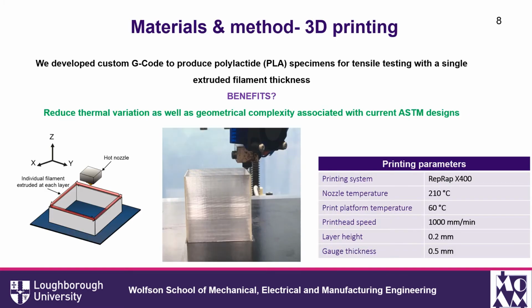To do so, we decided to print our own tensile testing specimen using the custom G-code developed by us. The benefit of using custom G-code rather than ASTM standards is reducing the thermal variation as well as geometrical complexity, which is normally known to be associated with the ASTM standard. The printing parameters are shown in the table on the right hand side, and then a schematic showing the toolpath for printing our boxes is here as well.